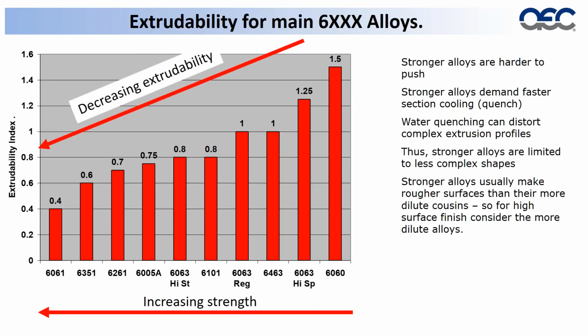Stronger alloys are harder to push. But the other thing here, which we haven't introduced so far, is that stronger alloys, when they come out of the press, they leave the press at about 1000 to 1040 degrees Fahrenheit. And for metallurgical reasons, for the strengthening of aluminum, it is important that they are quenched to 400 degrees Fahrenheit in under 1 minute. To do this, these stronger alloys like 6061 are pushed through a water bath. And it cools it down fast. You can hear the fizz as it goes in, and the section gets cooled tremendously.